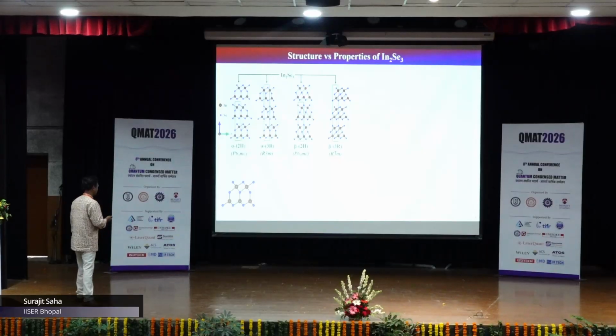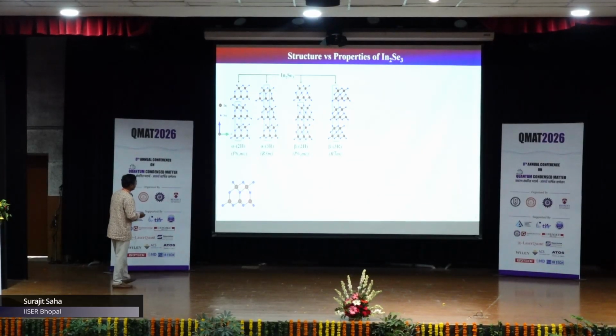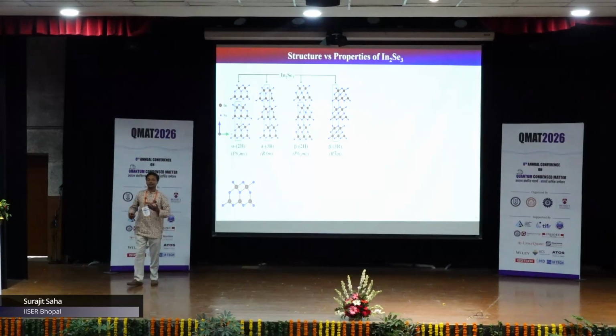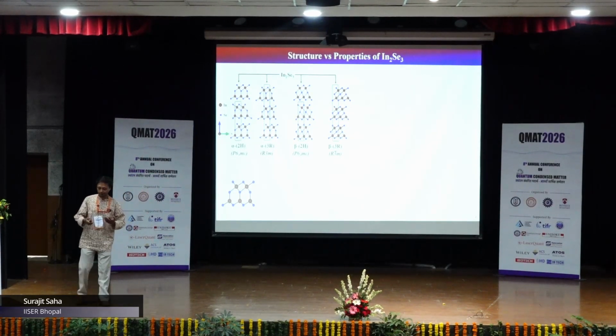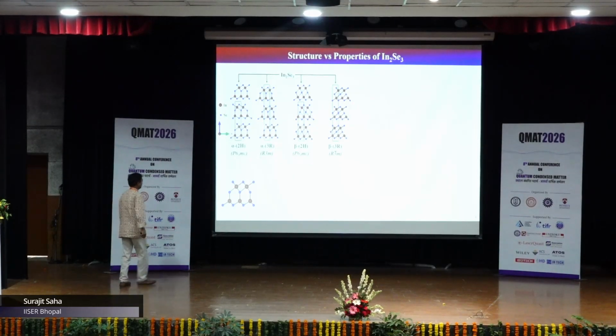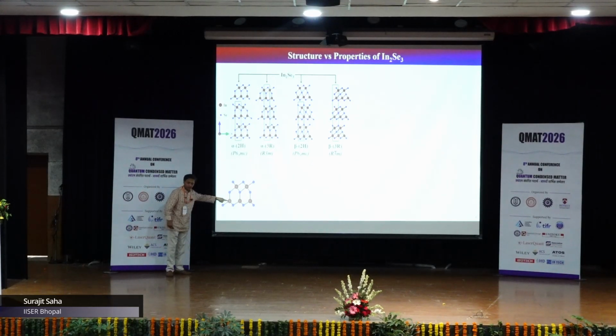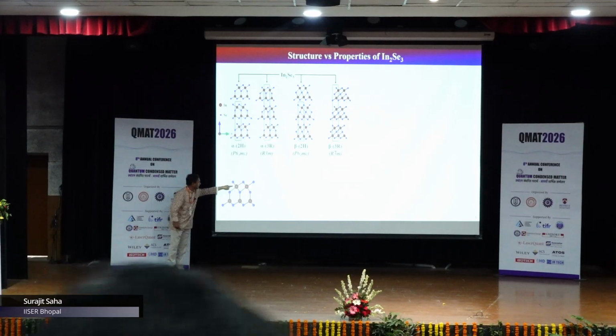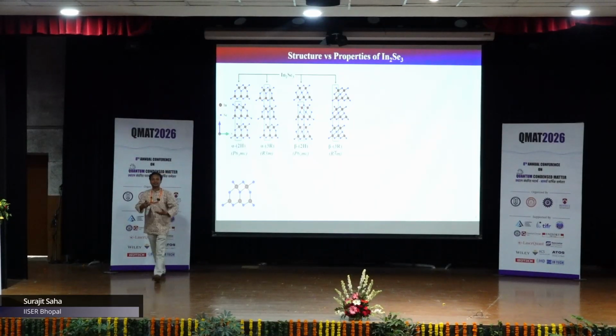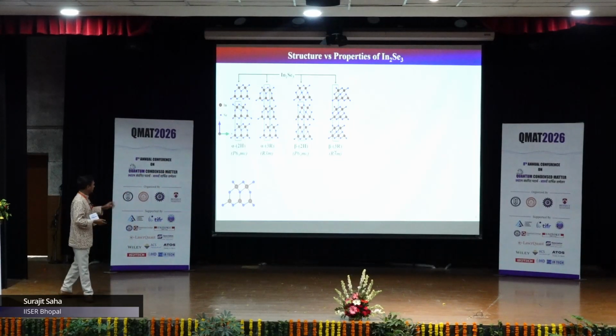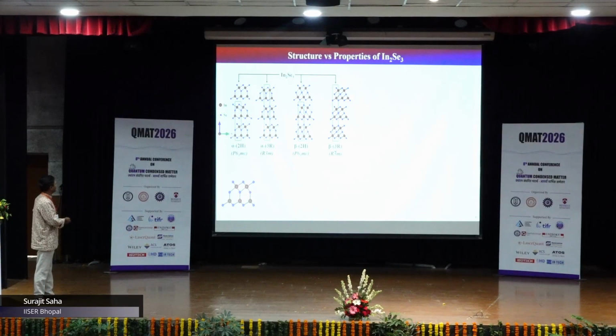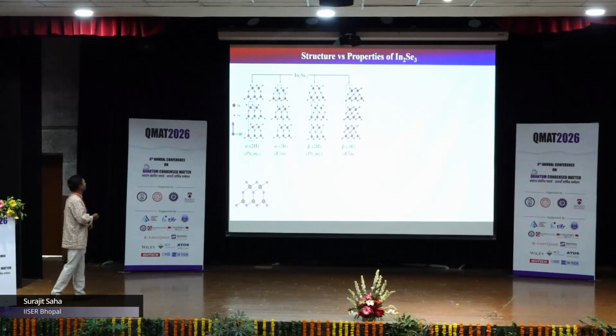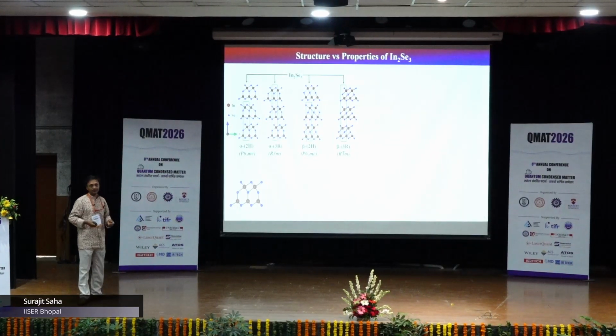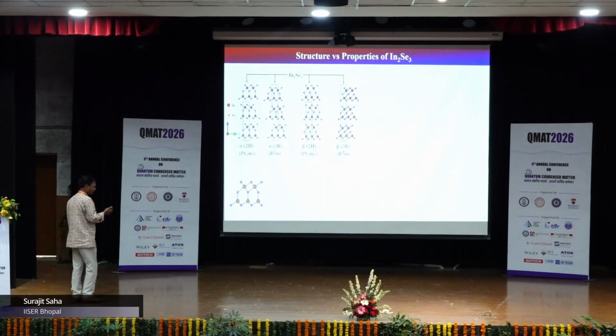Indium selenide, as you can see, has in every individual layer a quintuple layer, where there are 3 layers of selenium and 2 layers of indium. Now, something very important that I want to draw your attention to here. You can see this indium is tetrahedrally connected, and these 2 indiums are octahedrally connected. That makes this structure very unique. And this is the monolayer of it. Based on how this one layer is stacked with other layers, it can actually give these different polymorphs. And there are other polymorphs as well, which I'm not going to talk about today.